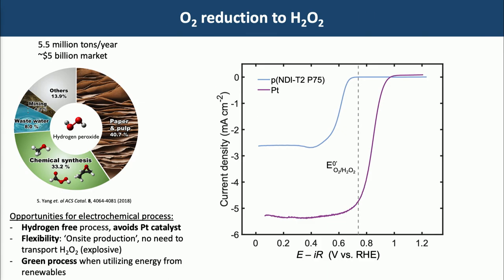So the example that we worked on with Will Chu's group is to reduce oxygen to hydrogen peroxide. Hydrogen peroxide is an interesting chemical for several reasons. It's used in multiple industries. It's actually dangerous to transport, so maybe you want to produce it locally. So being able to produce it locally by electrocatalysis is quite an attractive proposition. And you see there with our polymer, you have the current density there. This essentially is a proxy for the production of the hydrogen peroxide. And it doesn't have any noble metals.